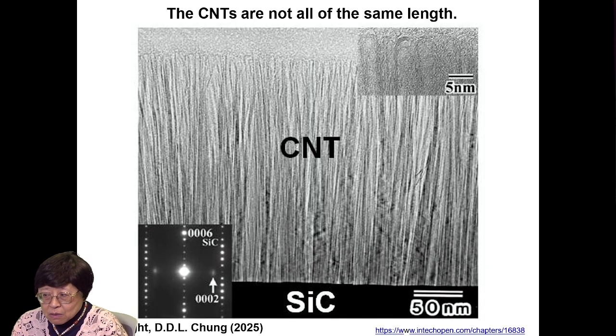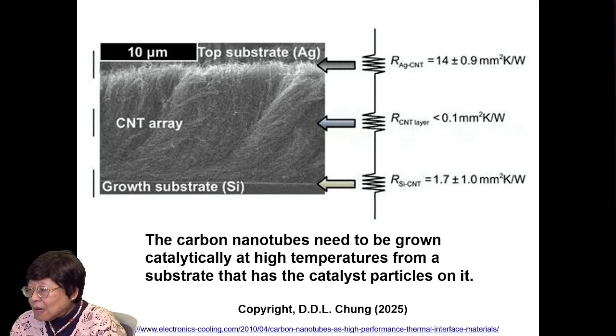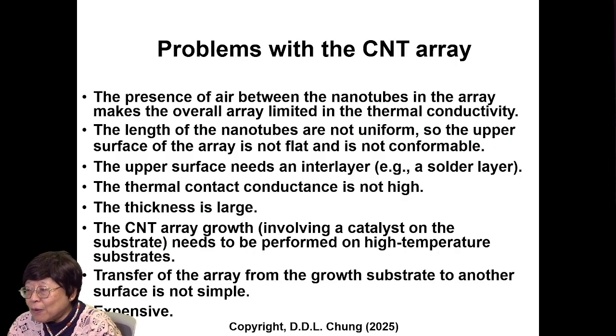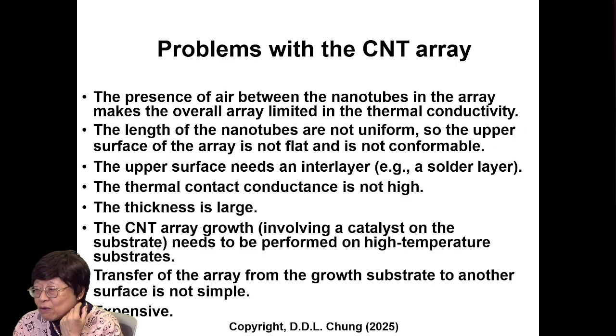However, there are problems. One is that the nanotubes are not all of the same length. Say the top is not flat. So you need to have an extra layer of something at the top because the top of the array is not flat. Now, the nanotubes need to be grown catalytically at high temperatures from a substrate that has the catalyst particles on it. And that high temperature of the growth limits the kinds of substrates that qualify. And that means that one needs to transfer the array after the growth to another substrate. And that transfer is not simple.